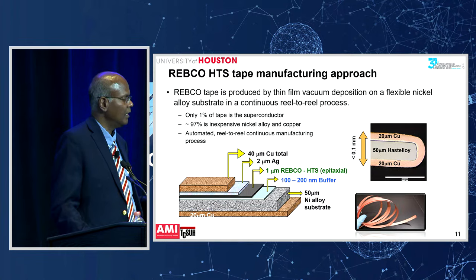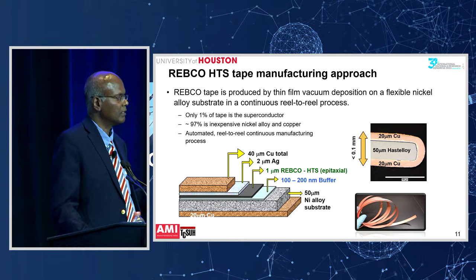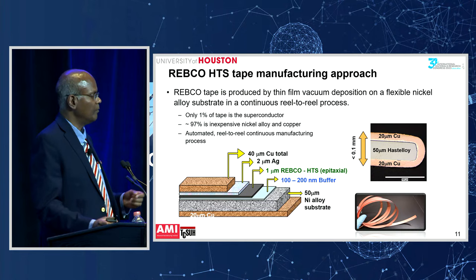It's only about 1 to 2 microns thick. Because the superconductor can carry so much current, you don't need much of it. You need only a thin film of that. And then most of it, as you can see, is copper and nickel alloy.